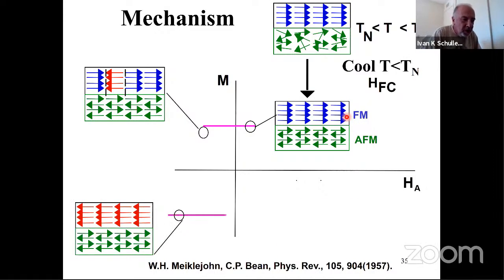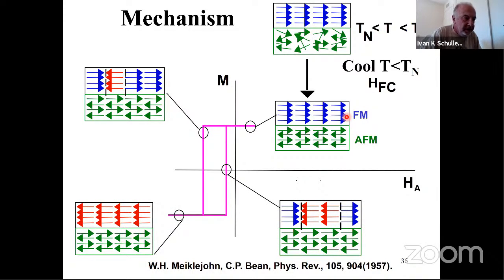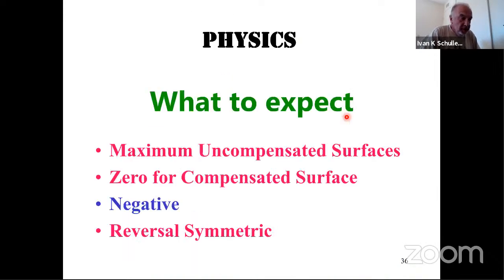And so let's see what one would expect. This is the original explanation by Meiklejohn and Bean. So what would you expect? What you would expect is basically four things. You would expect that the exchange bias should be maximum for uncompensated surfaces. I'll show you in a second what I mean by uncompensated surfaces, but what I mean by that is that the magnetic moment of the surface should be non-zero. That's what an uncompensated surface is. It should be zero for a compensated surface. Since this is like applying an internal field, it should always be negative. And all magnetic materials known to man have a symmetric reversal.